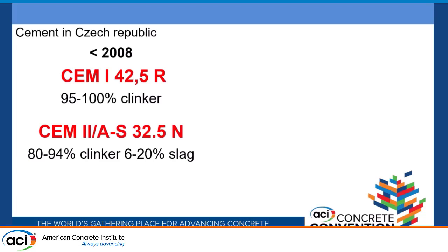Until 2008, we had CEM 1 42.5 R, where R is like rapid. So that was 95% of the cement. And as you can see on this slide, it was 95 to 100% clinker. Yeah? So this is cement that was used for, let's say, durable concrete, 0.45 water cement ratio and below. Another cement type that was widely present in Czech Republic was CEM 2 A-S 32.5 N. N means normal strength. And that was 80 to 94% clinker and 6 to 20% slag. So this cement was typical for low strength concrete without special durability requirements.